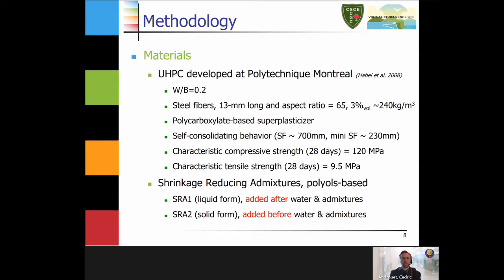This material has a characteristic compressive strength at 28 days of 120 MPa and a characteristic tensile strength at 28 days of 9.5 MPa. For the shrinkage reducing admixtures we use, those are 2 polyol-based materials, and those are the same material. One is supplied in liquid form and the other one is supplied in solid form. So the SRA1, supplied in liquid form, would be added after water and admixtures in the mix, while the SRA2, supplied in solid form, would be added with all the dry materials before water and admixtures are added to the mix.